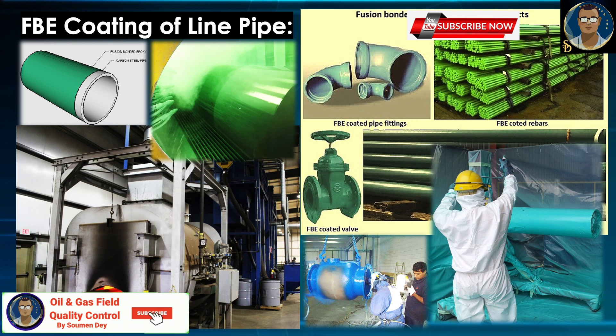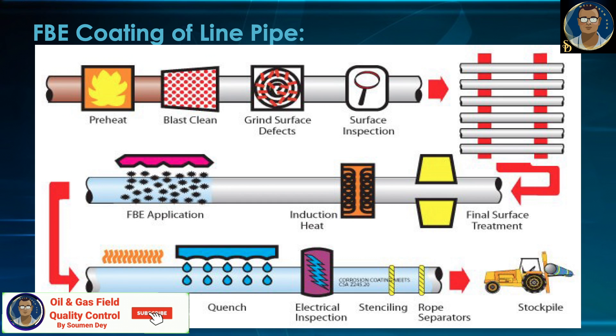This is the process through which an epoxy becomes cross-linked as polymer strands form into a hardened structure. This property of epoxies is used in fusion bonded epoxy coating over pipes to provide long-term corrosion resistance and protection under moderate operating temperatures, ranging from 30°C to 110°C. The resin and hardener components in the dry powder FBE stock remain unreacted at normal storage conditions. At typical coating application temperatures, generally in the range of 180°C to 250°C, the contents of the powder melt and transform to a liquid form.